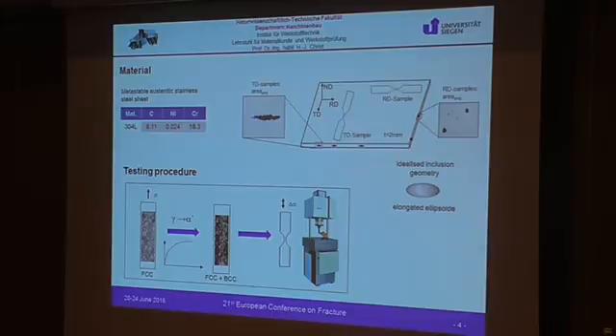In the as-received condition, the recrystallized condition, the material has a fully austenitic microstructure, but during the plastic deformation, some parts of the microstructure can transform to alpha prime martensite, so that we get a quasi-duplex microstructure consisting of different amounts of austenite and martensite. We can regulate the amount of martensite by controlling some parameters of the predeformation, like the deformation degree or the environmental temperature. After that, fatigue samples were machined and tested in the high cycle and very high cycle fatigue region.